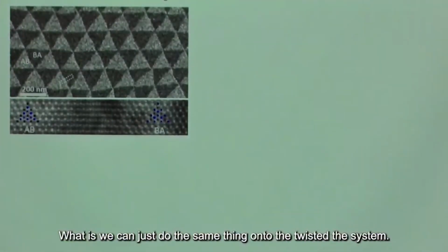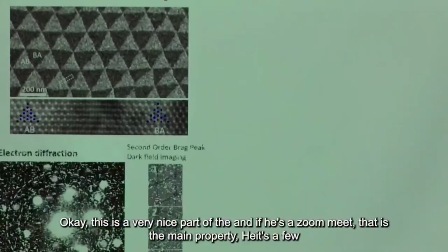We can do the same thing on the twisted system. Again, this is a very nice part of twisted bilayer graphene. You can see that the AB-BA domain boundary is there, and if you zoom into this domain boundary, indeed, along this length scale of a few nanometers, about 10 nanometers, there's a slippage of the atomic registry, showing that indeed there is a structural soliton, or in our language now, a dislocation line passing through.